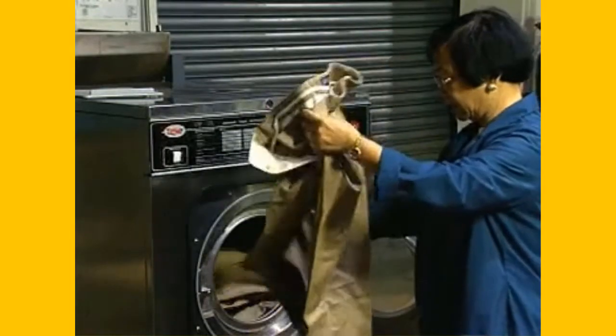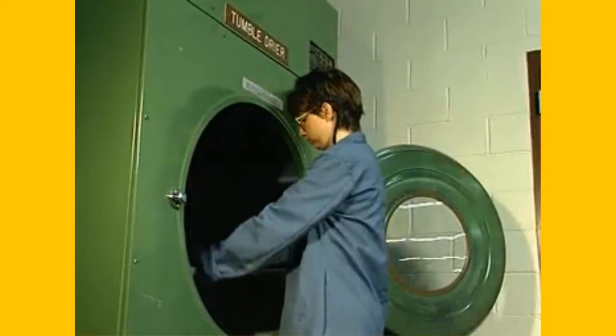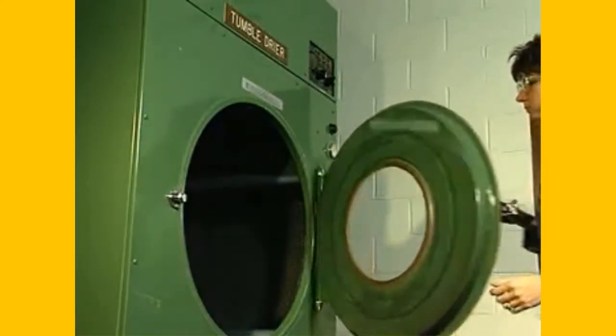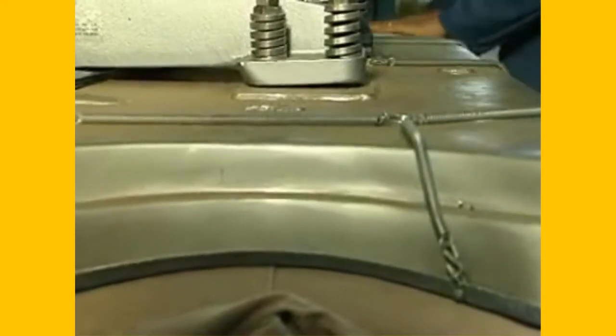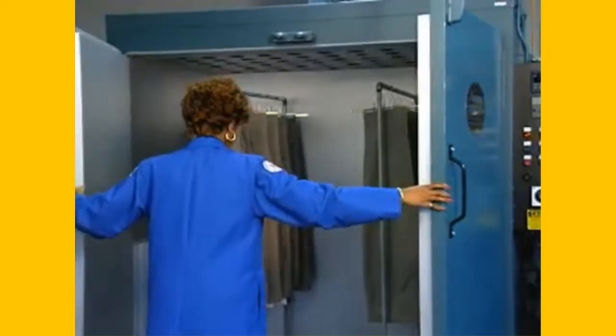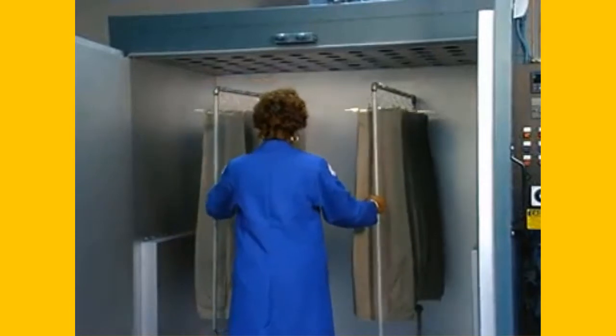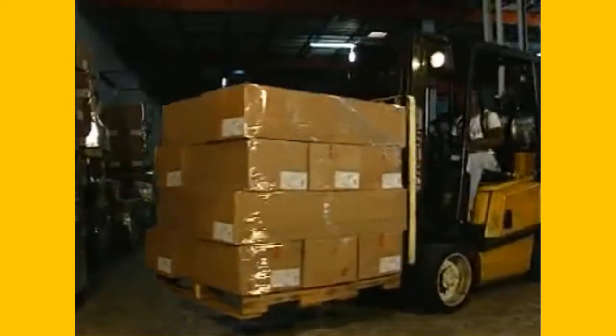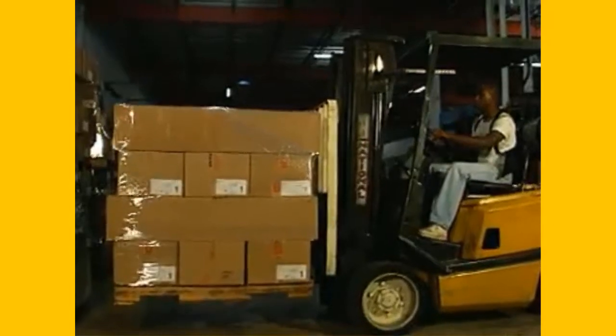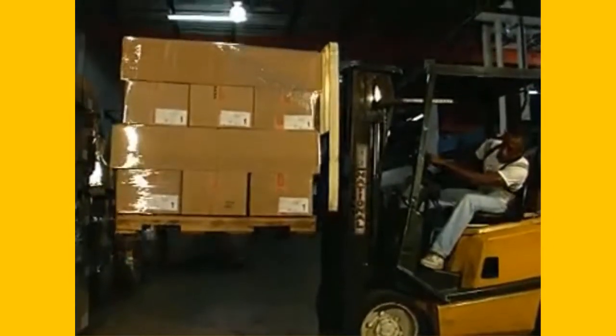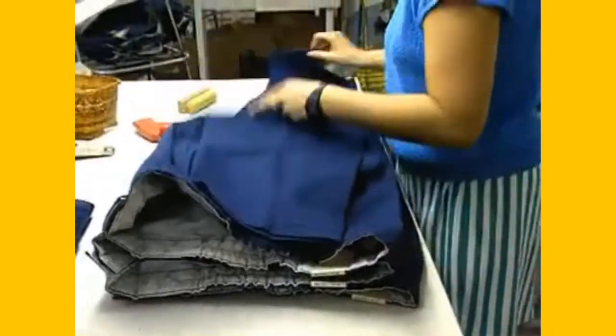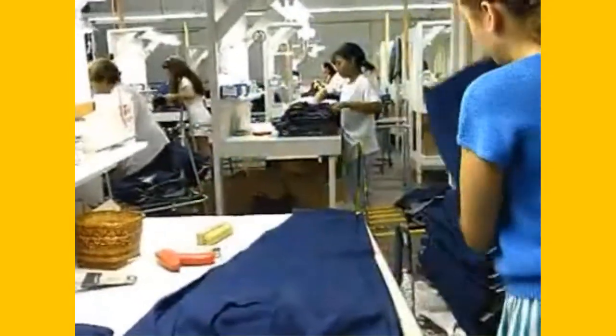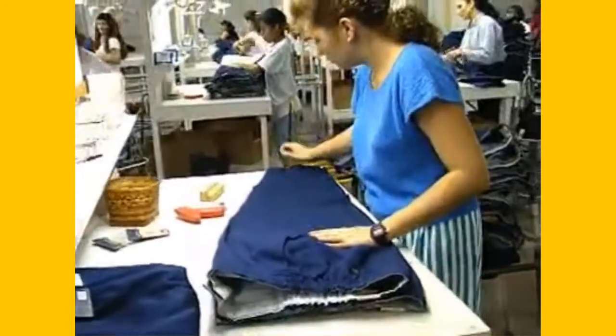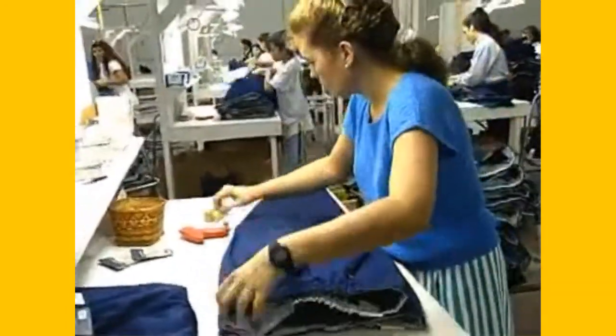One method is garment dip. Garments that are first cut and sewn are immersed in a chemical bath. After this, the garment is tumble-dried at a low temperature, which also pre-shrinks the fabric. Next, the garment is pressed. Finally, the garment goes to an oven for curing, which is when the resin chemically reacts. A benefit of this process is better inventory control, because garments are finished only when orders arrive. The garments produced by applying resins and garment dipping shrink less and have better fit. There is a softer hand than that produced by the conventional post-cure method.